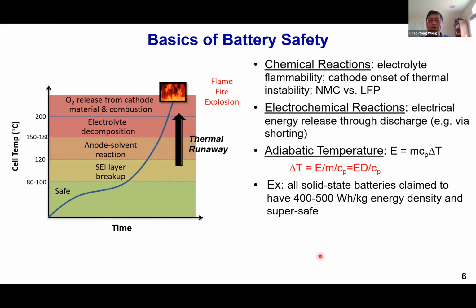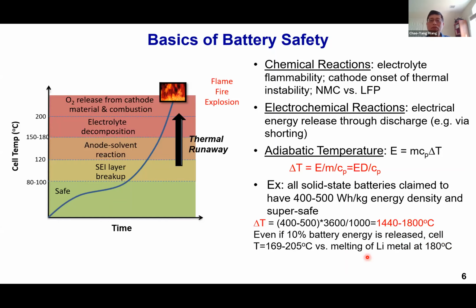Solid state batteries, we hear about every day in the media or in research papers, and they claim to have 400 to 500 watt hour per kg energy density and at the same time super safe. But if you calculate the adiabatic temperature rise, it's between 1400 to 1800 degrees Celsius. So obviously everything is gone, even if you have a very non-flammable electrolyte, solid electrolyte, right? So we have to be careful when you claim that the solid-state batteries are safe.